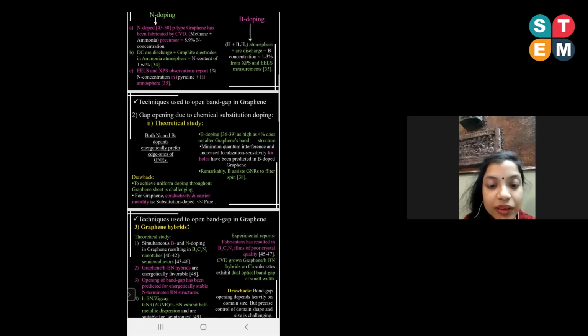And this is particularly evident for graphene nanoribbons. Boron doping as high as 4% does not even alter the band structure of graphene, according to these DFT first principle calculations, let alone giving rise to a band gap. Minimum quantum interference and increased localization sensitivity may be the reason for this. Remarkably, boron assists graphene nanoribbons to filter their spin. Therefore, this boron doping interferes with the spin state of graphene.